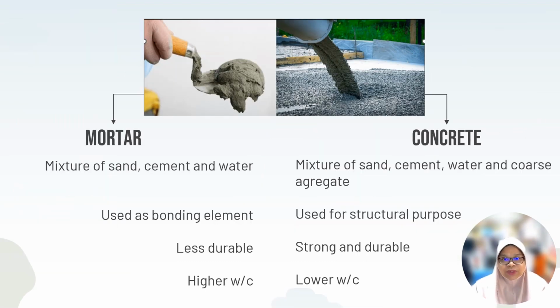What is the difference between concrete and mortar? In the picture shown, mortar looks like a thick paste. This is because mortar is a mixture of sand, cement, and water. Concrete, on the other hand, looks rough because it is a mixture of sand, cement, water, and coarse aggregate. Apart from that, mortar is used as a binder, while concrete is used for structural purposes. The difference also lies in the consumption of water during the mixing process, since mortar requires more water than concrete.